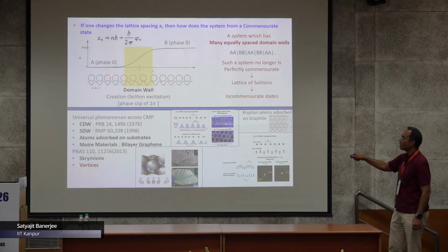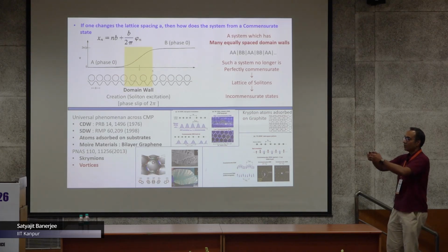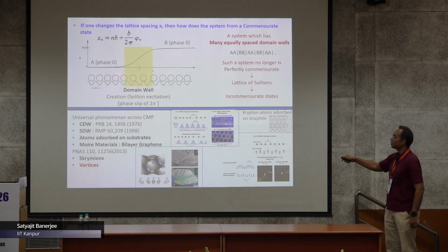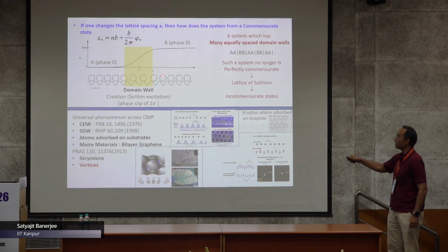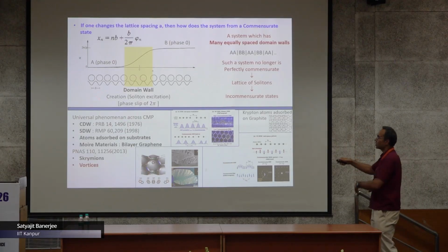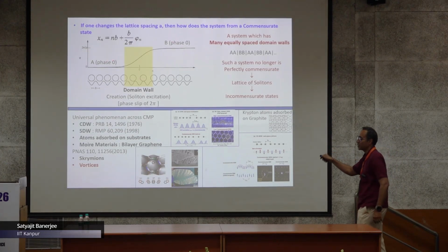They will form an ordered state, like 1 particle per hole, 1 particle per potential, and then the elastic energy will actually start increasing in this region, and again it will match with the system, so you have a domain wall formation.